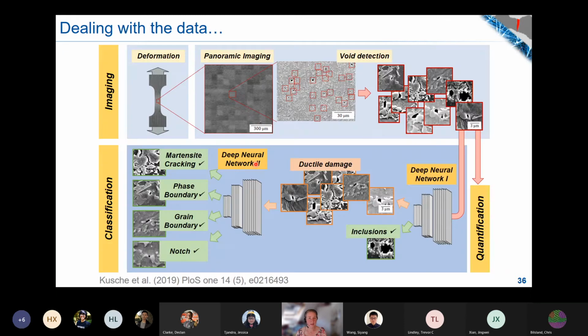What do we do then? We end up with a lot of image data, and what we really need is to be able to deal with that and concentrate on understanding what the material does and not have people spend all their time looking at micrographs. So we deform a sample, we put the sample together into one panorama, and then we use what you would normally use, some algorithm for void detection. So for example, in case of damage, pores essentially, and cracks, we look for dark pixels that are clustered together. We can quantify those, of course, in terms of the area, for example, or individual size.